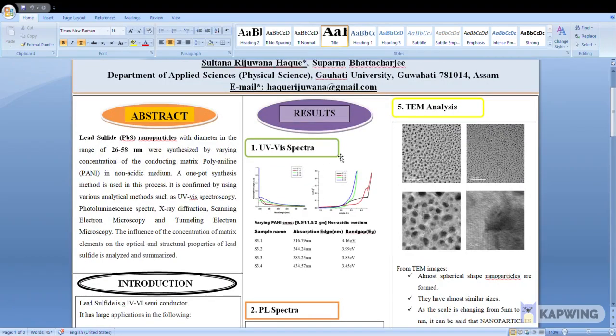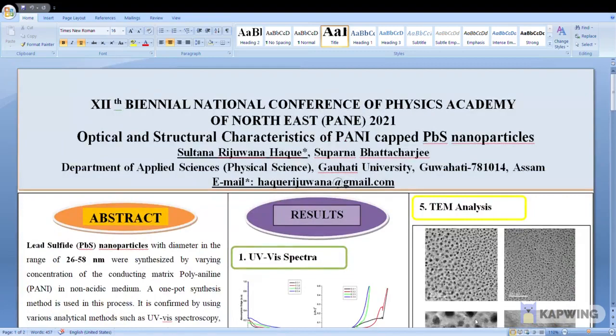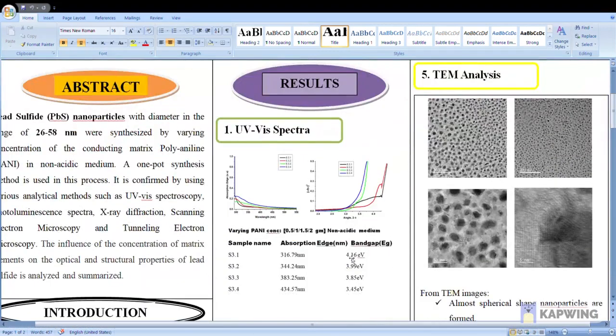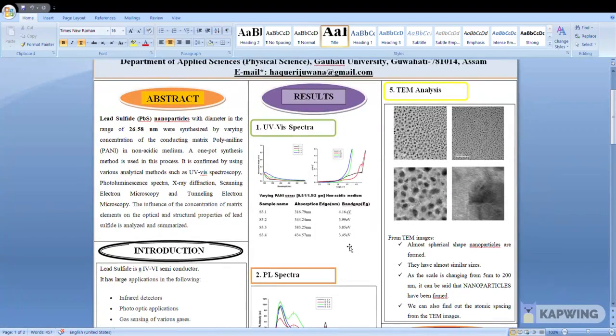To analyze whether the lead sulfide nanoparticles are formed or not, we have used analytical methods like UV visible spectra, PL spectra, XRD, SEM and TEM. From UV visible spectra, we can see in the figure that the absorption edges of the samples lie in the range from 316.79 nanometer to 434.57 nanometer. The blue shifting of absorption edges as compared to the bulk lead sulfide showed the formation of nanoparticles.